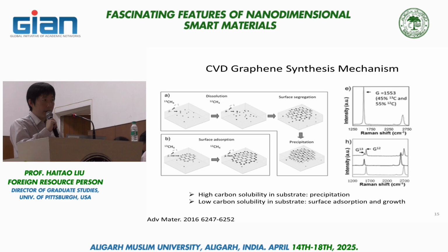Okay? So in that case, if you look at the Raman spectrum, you get a single peak, because remember, Raman is the vibration, and vibration depends on the atomic weight of the atoms. So if you have different isotopes, ideally you would have different frequencies of vibration. But if they're all mixed together, then it will be averaged out. However, if you have this adsorption and growth mechanism, if bulk solubility is low, then whichever is flown first, let's say the carbon 12 methane, will produce carbon 12 graphene. And then if you switch to a methane with a different carbon isotope, you'll get another layer, another run of carbon 13 graphene. And in this case, you'll get two peaks in the Raman spectrum instead of one. Okay. So by using this approach, people have definitively figured out the very different growth mechanisms.